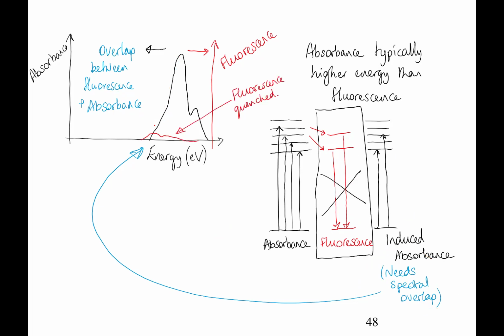However, what frequently happens, and certainly this happens with the Squaraines, and maybe this is again revealing the punchline too quickly, but when we get aggregates, when these molecules pack tightly together, it turns out that actually this fluorescence is greatly quenched. Okay, it's greatly quenched, and so now we've lost all the overlap. We've lost that overlap integral, and we would think the energy transfer would be greatly reduced.